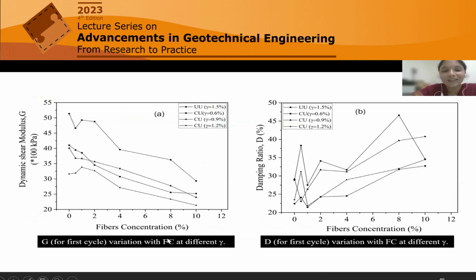If you see here, with the increase in fiber content we get improvement in strength in the static case, but not in the dynamic case. Shear modulus is decreasing and damping ratio is increasing. Here also you can see a random trend, for both UU and CU cases. This is because, even though we repeated the tests many times, after mixing the fiber into the MSW fines we can make the sample, but the fibers are like threads. They can take compression, but in the extension, tension cycle the interaction, or interlocking, is lacking, particularly in the dynamic loading case.